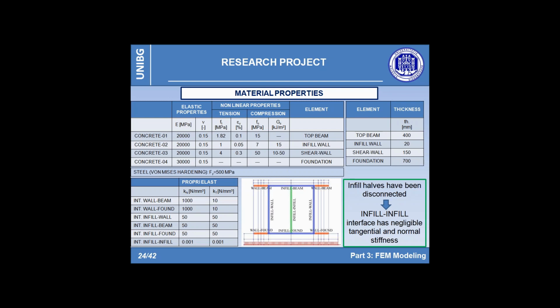Concerning the steel reinforcement, it has been decided to adopt a von Mises model with no hardening and a yield strength equal to 500 megapascal, thus describing an elastic perfectly plastic material.